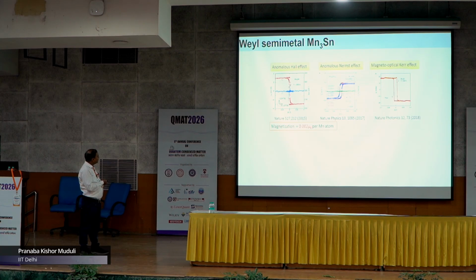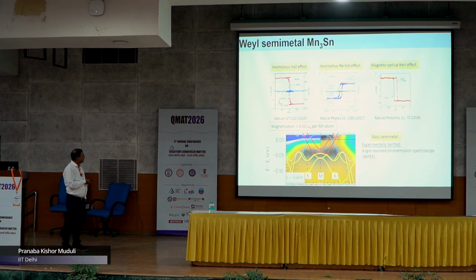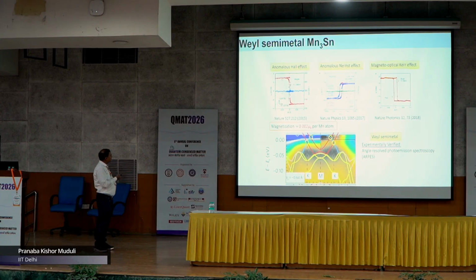And the reason why it's happening is because this is related to the quantum property of the material, which has been experimentally verified by the presence of these Weyl points near the Fermi energy. Because of these Weyl points, there is a large Berry curvature which drives these effects. This cannot be explained by, of course, in the real system there is a little bit of magnetic moment with the manganese, and this cannot be used to explain this property. You need this quantum property to explain this behavior.